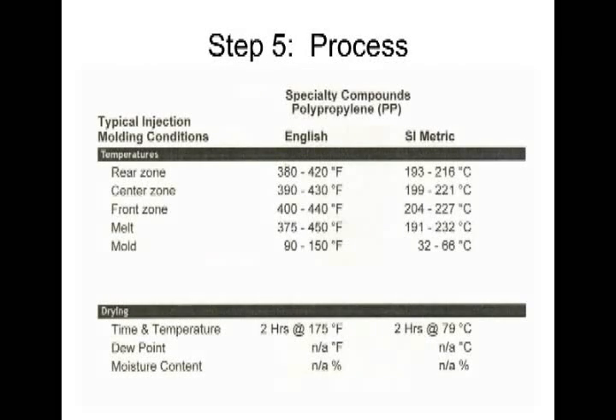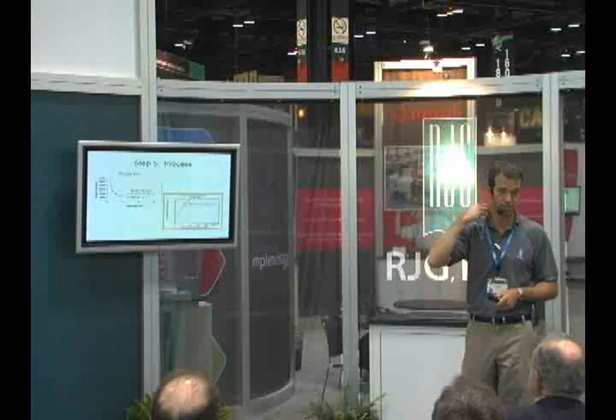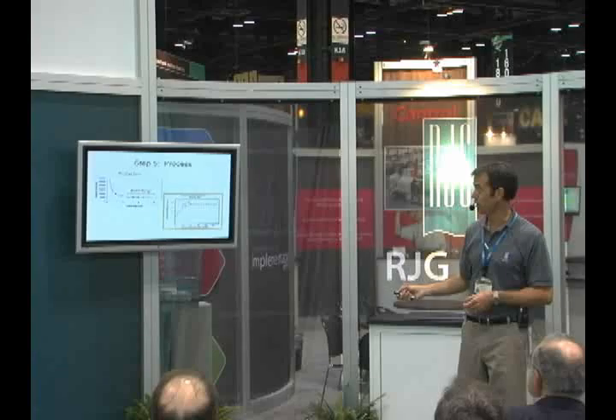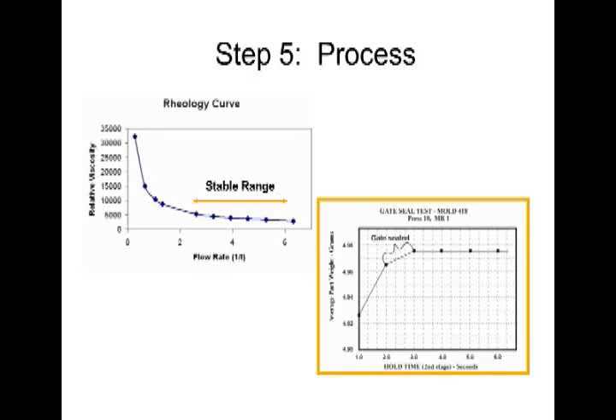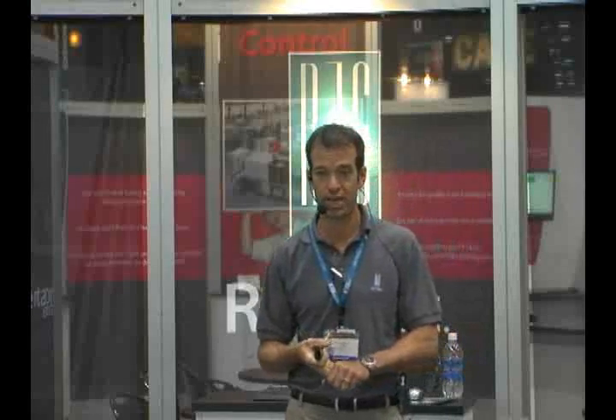We don't want to get into a corner where we're operating high or low, because then we don't have any adjustments once we need to compensate for variation in the process. Those familiar with scientific molding will probably be familiar with a rheology curve or viscosity shear rate curve. There's a methodology in scientific molding that allows you to do a 10-shot study to create the appropriate data to document that curve, and what comes out of that are the shear rates most effective for the mold, material, and machine configuration you're using.